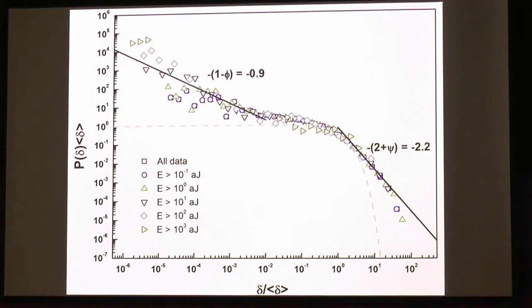So you have, inside, these sudden changes of the strain. And you can see here the probability for time delay between the initial jerk and the secondary jerk, which is basically what we steal from the geophysicists as the aftershocks. So this one is the aftershock regime. This one is a continuous regime. And this regime here is the random regime.